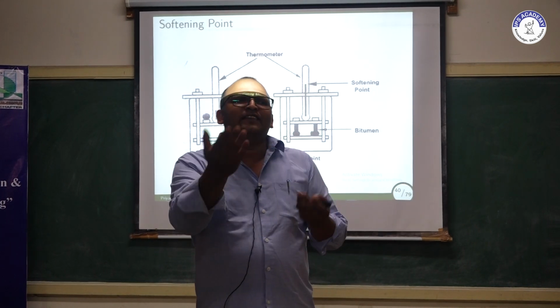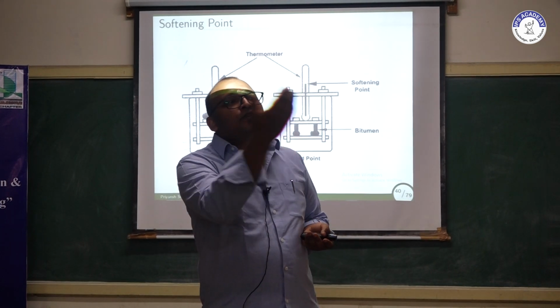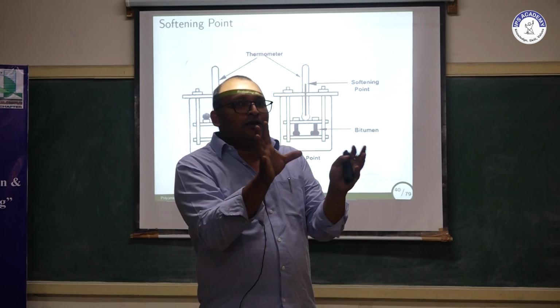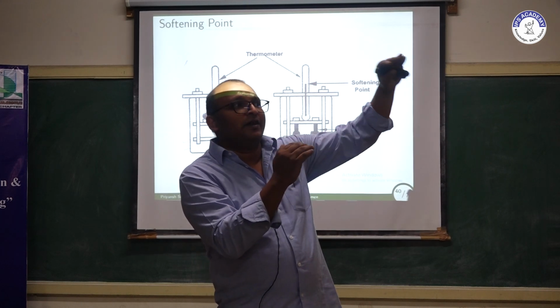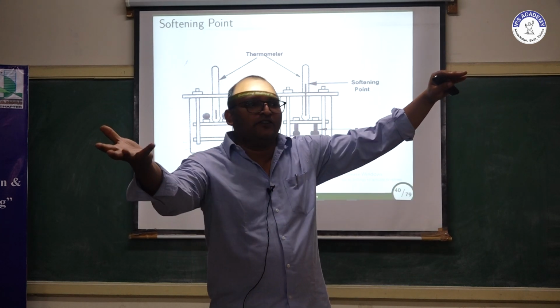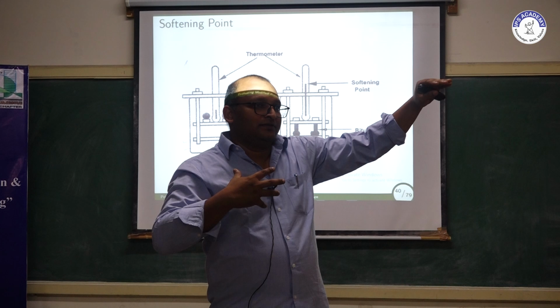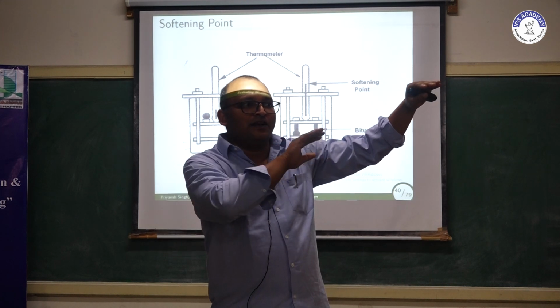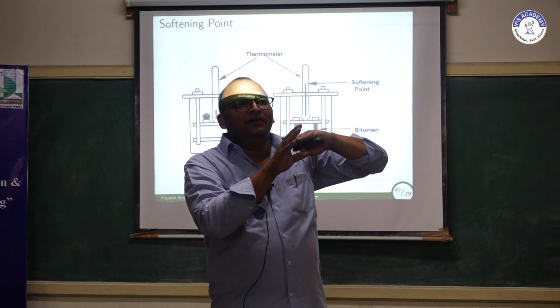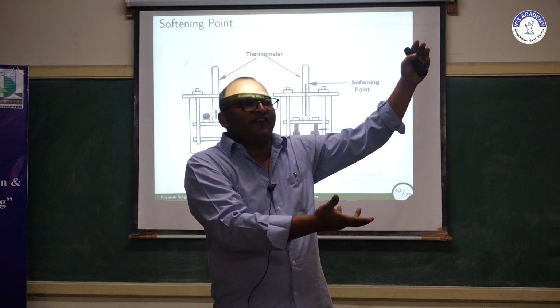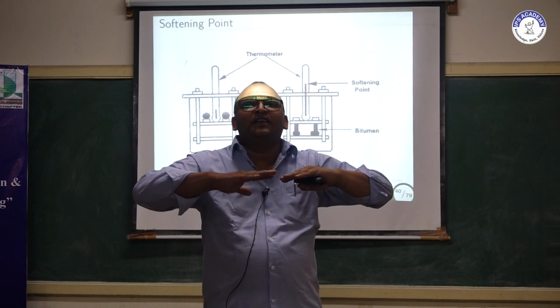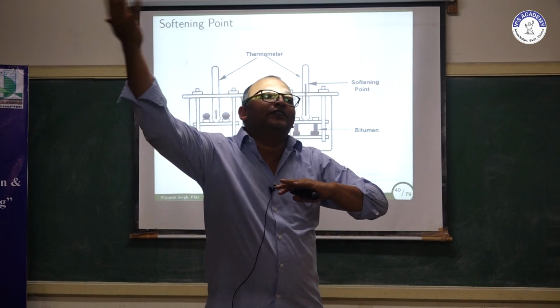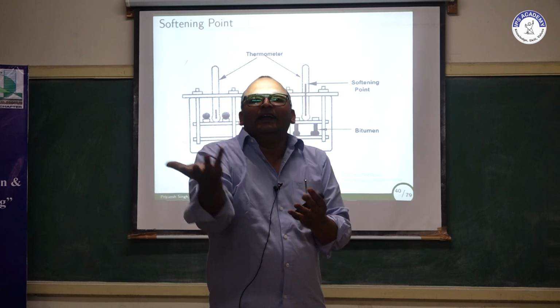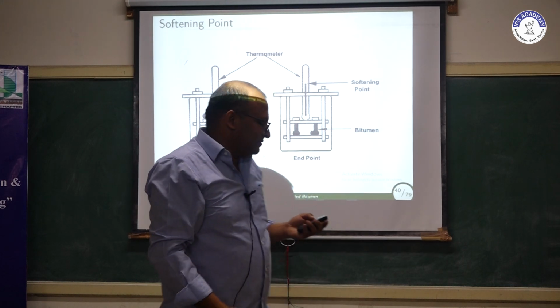So this softening point is actually an indirect measurement of viscosity. That is, when a binder attains a particular viscosity, that temperature we want to signify. So it's the reverse of penetration. In penetration, we measure viscosity at 25, but here we want to measure at what temperature a particular viscosity is attained.